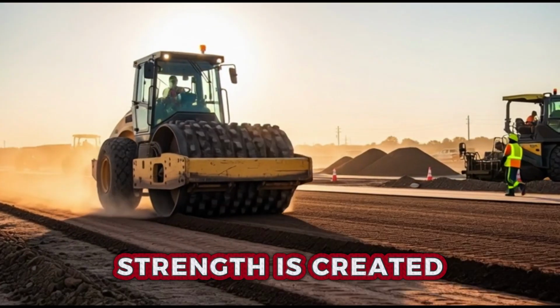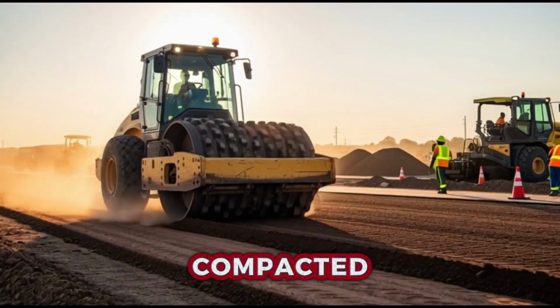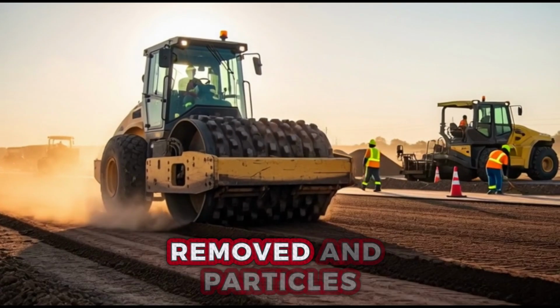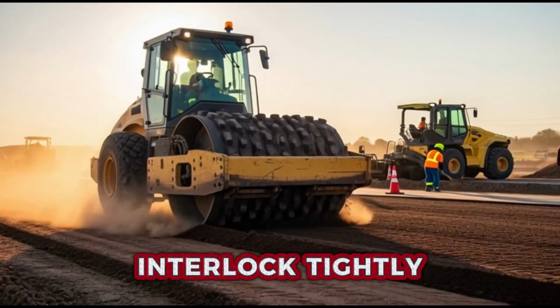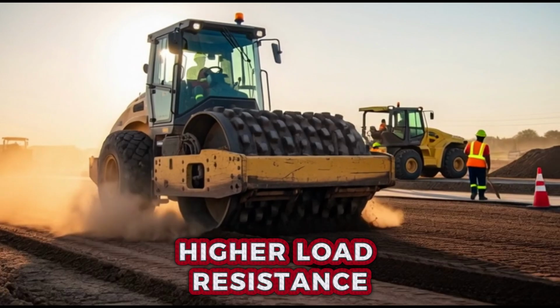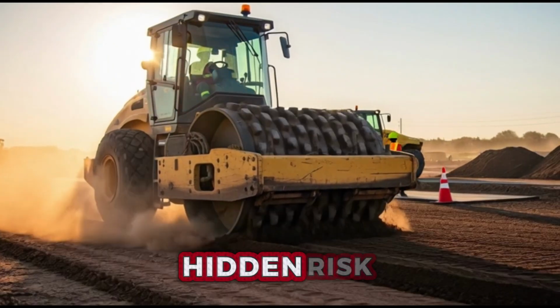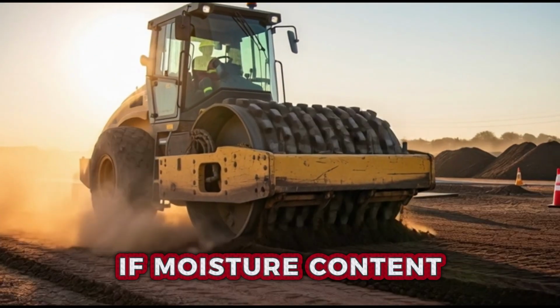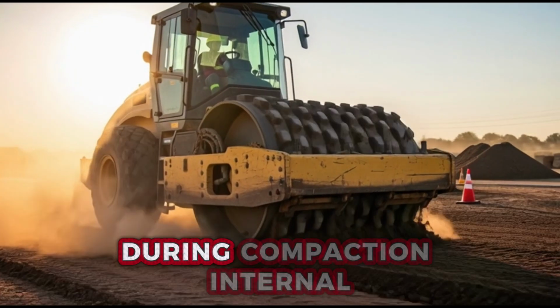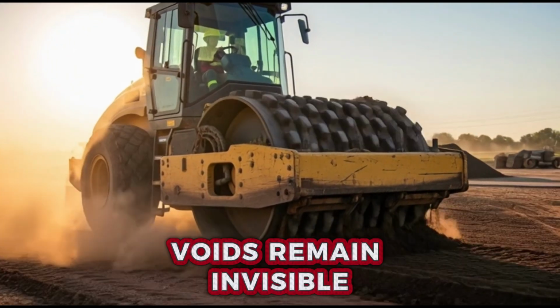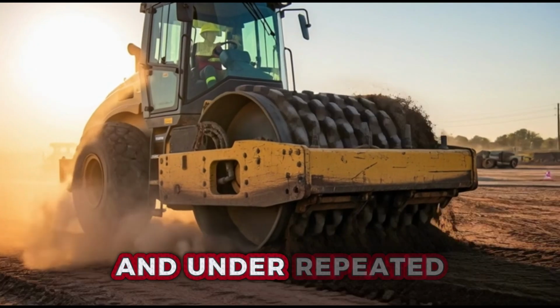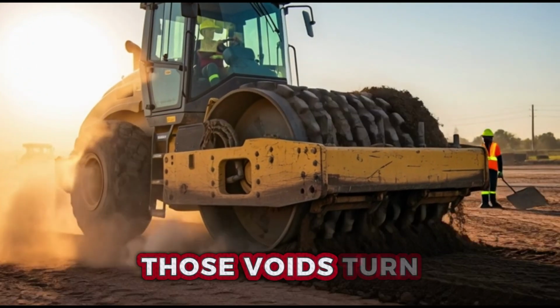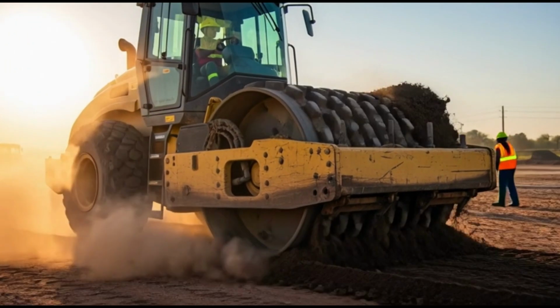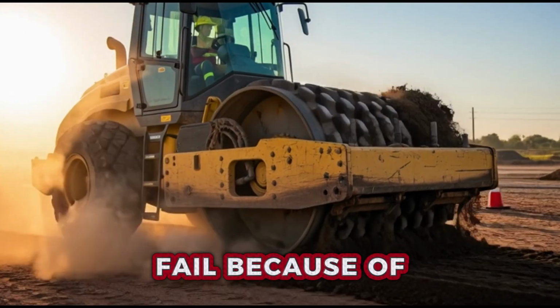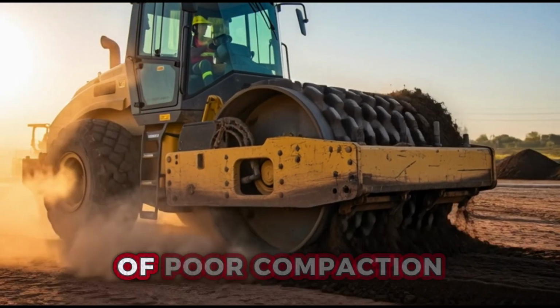Compaction is where strength is created. When soil is compacted, air voids are removed and particles interlock tightly. Higher density means higher load resistance. But here's the hidden risk. If moisture content is too high or too low during compaction, internal voids remain invisible. And under repeated traffic loading, those voids turn into structural weaknesses. Many roads don't fail because of bad asphalt. They fail because of poor compaction.